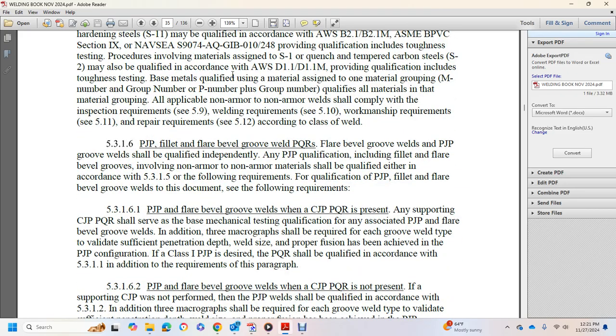PJP with the flare bevel groove weld, where the CJP performance qualification record is present. Any supporting CJP performance qualification record with the base of the mechanical testing qualification associated with the PJP flare bevel groove weld, additional 3 macrographs should be required with each groove weld to show the depth of the penetration and the depth of the weld, with proper fusion, and to achieve the PJP configuration. Class 1 PJP with the desired procedure qualification record should be in accordance with the 5.3.1.1, in addition